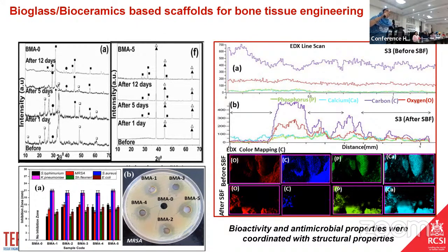And if you get the peak at 31.8, which is the fingerprint peak of hydroxyapatite, it means the sample is going to produce hydroxyapatite on the surface of the sample. And then from SEM and EDX, I don't know how many PhD students are here. In EDX, we can find out the concentration of different ions, like how much calcium and how much phosphorus are in your sample, before and after. You can see the calcium and phosphorus concentration increased to 400, and before it was below 100. So calcium and phosphorus start depositing on the surface of the sample.